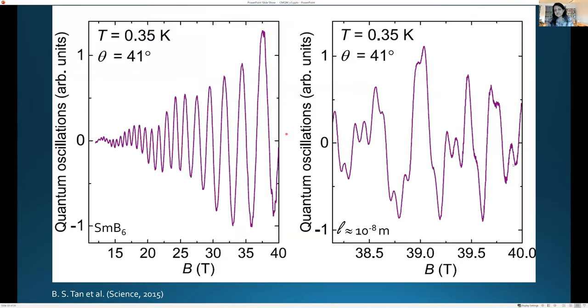But one of the things that actually makes it convincing that it's not from a tiny pocket or a tiny inclusion is that not only do we see low frequency oscillations, so this frequency is a few hundreds of Tesla, but we also see, if you blow up at high magnetic fields, so now a background has been subtracted, high frequency oscillations, and this is now over 10,000 Tesla.